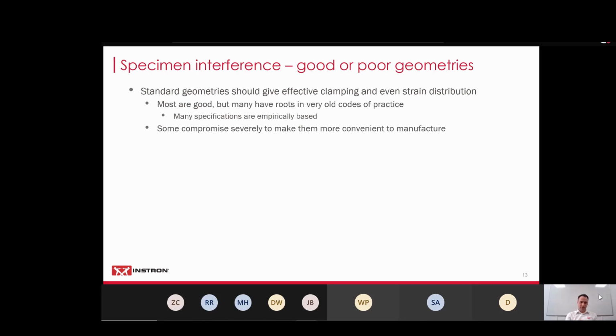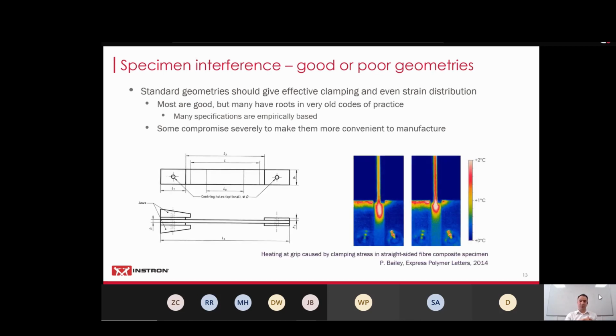Occasionally, however, you will find some standard specimens which are still there and lurking, and they compromise quite severely. My pet hate on this is parallel-sided, straight-sided composite test specimens. And these come out of the days when really you couldn't get a very good machining unless you used a diamond saw, and obviously you can't make a waisted specimen using a circular saw. That doesn't work. The outcome of this is that there is no good reason for them to break anywhere other than at the clamping point.